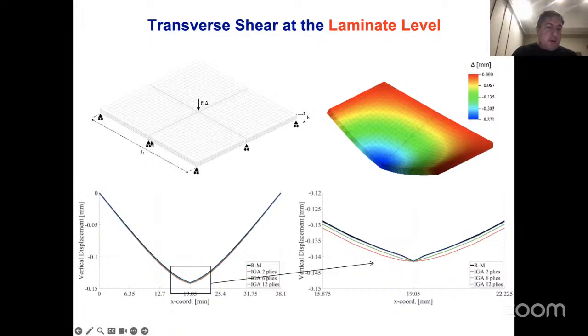And so if you plot the vertical displacement from side to side, you get a curve that looks like this. And here we're computing a solution that's consistent with the Reissner-Mindlin shell theory, which takes transverse shear into account. And here is an isogeometric solution using 2 plies, 6 plies, and 12 plies. And so globally, the solutions are the same. But of course, something happens under the point load. And if you look at the Reissner-Mindlin solution, you can actually see localization here, deformation under the point load.